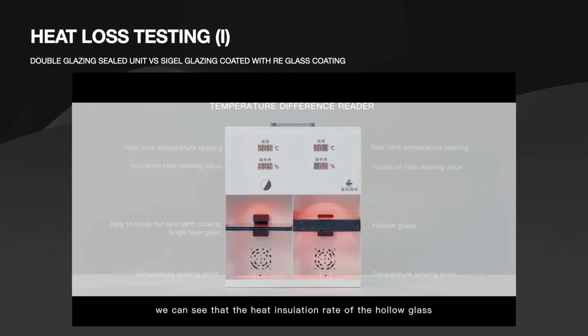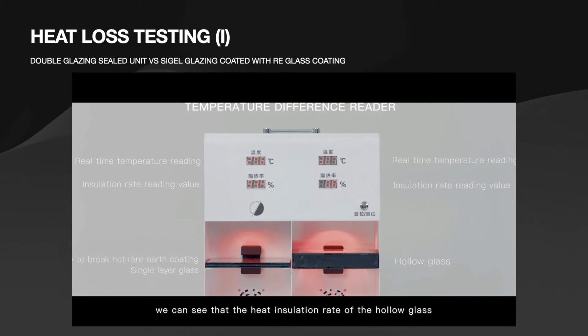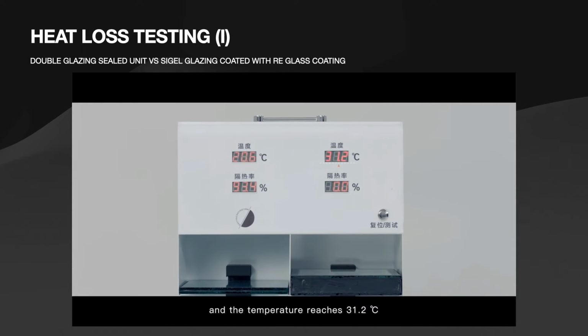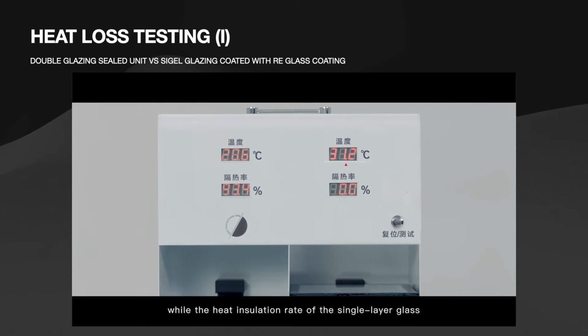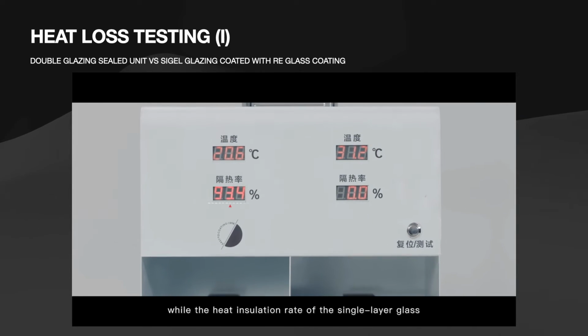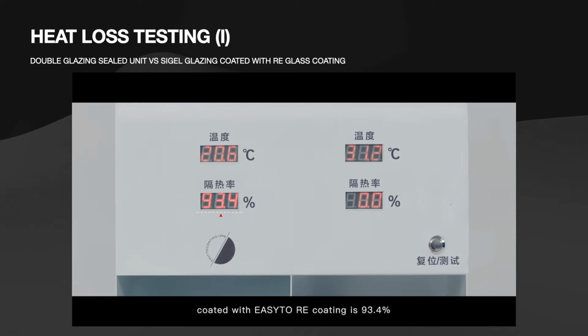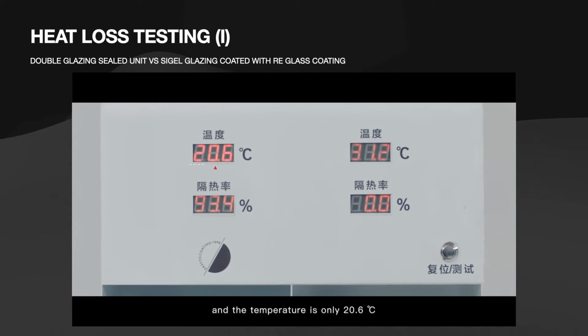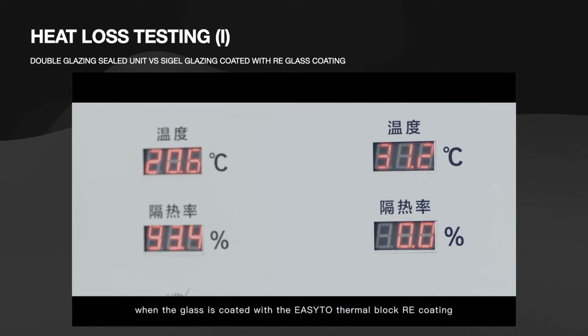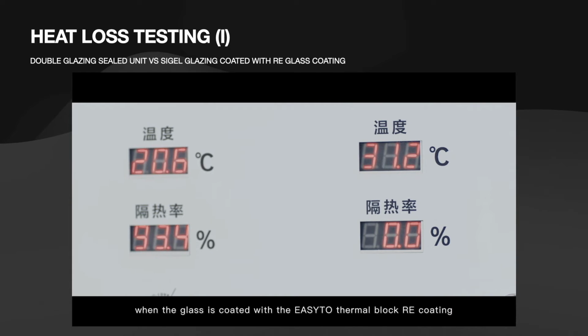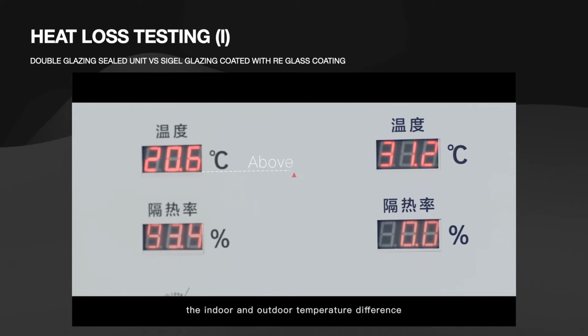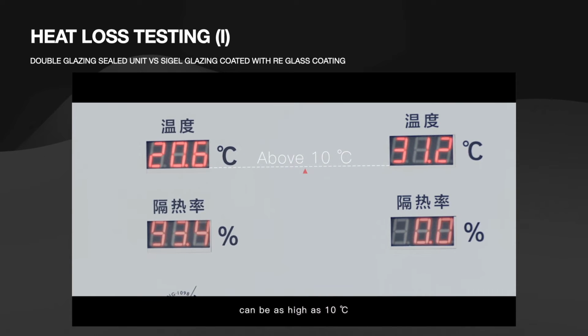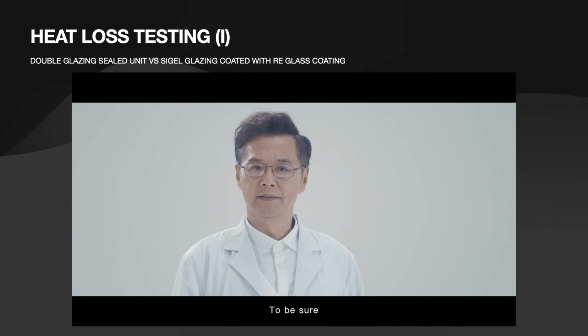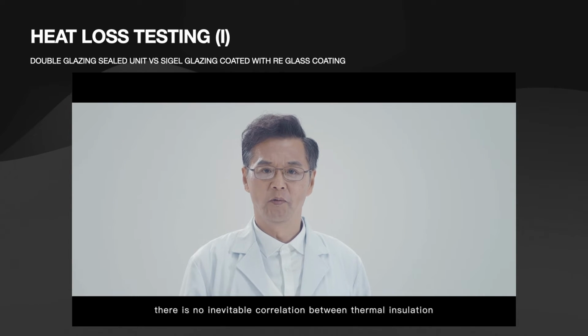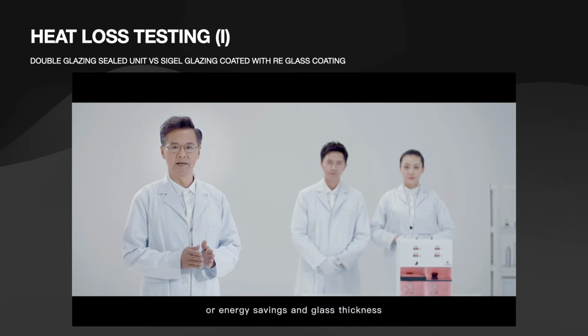1 minute later, we can see that the heat insulation rate of the hollow glass is almost zero, and the temperature reaches 31.2 degrees Celsius, while the heat insulation rate of the single-layer glass coated with EASYTO RE coating is 93.4%, and the temperature is only 20.6 degrees Celsius. That is to say, when the glass is coated with the EASYTO Thermoblock RE coating, the indoor and outdoor temperature difference can be as high as 10 degrees Celsius. To be sure, there is no inevitable correlation between thermal insulation or energy savings and glass thickness.